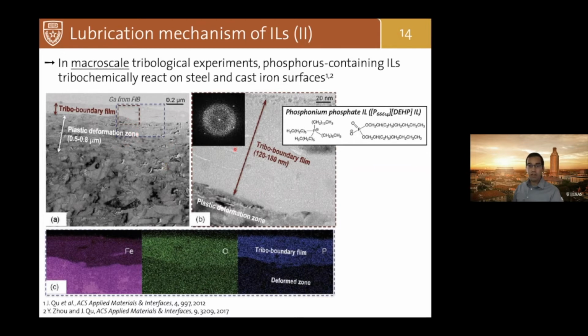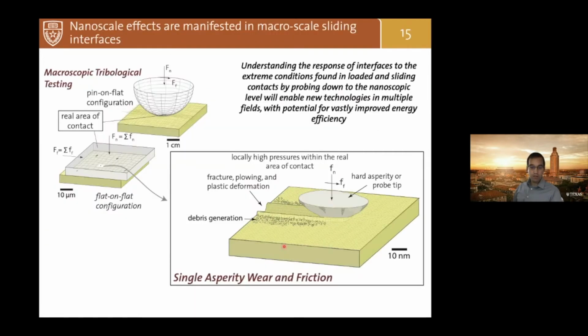At the bottom here, you have steel, and then you have this tribo boundary film. And what researchers from Oak Ridge showed is that in the case of this phosphonium phosphate ionic liquid, you have the formation of this phosphate-rich layer that actually prevents wear and leads to low friction in macro scale tribological experiments. So clearly here we have a length scale problem. At the nanoscale we have some information, and at the macro scale we have some other mechanism coming into play. So that's exactly what we wanted to do to start with in my lab.